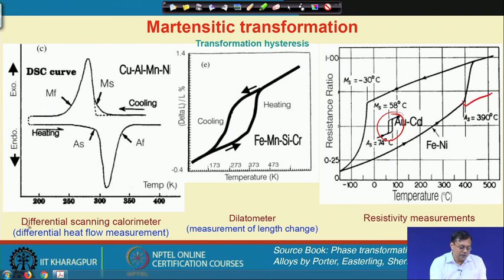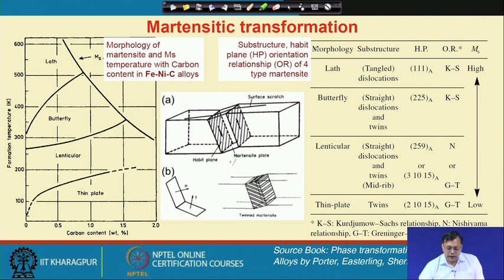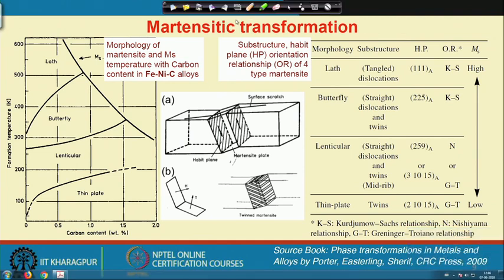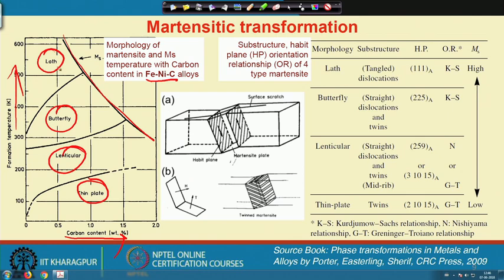So, these are differential scanning calorimeter plots, or dilatometer, or resistivity measurements, that show such features. However, the morphology of the martensite could also be a little different. In this particular slide I show you that in the case of an iron nickel carbon system, if we change the carbon content and the transformation temperature changes, the martensitic start temperature begins here, then we get these 4 different morphologies which I discussed with you just a few minutes ago: lath, butterfly, lenticular or thin plate. And these different morphologies are involved with different kinds of substructure. A substructure means, for example, tangled dislocations, or dislocation and twin. So, not only twins can be involved in this process. In a lath we see only dislocations, whereas in the case of a thin plate only twins are involved.